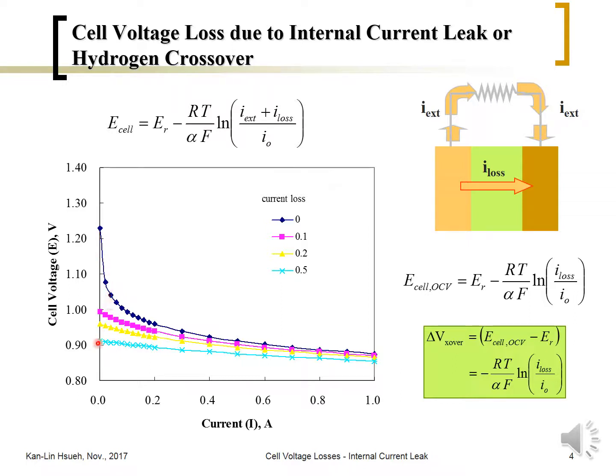So if we build a fuel cell or battery and find the cell voltage OCV is much lower than expected, definitely it has internal leakage current or the electrode has some way shorted out.